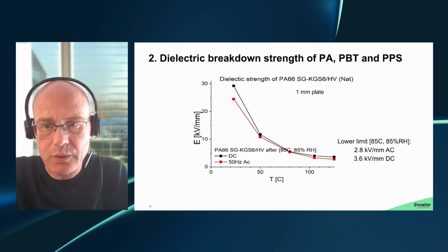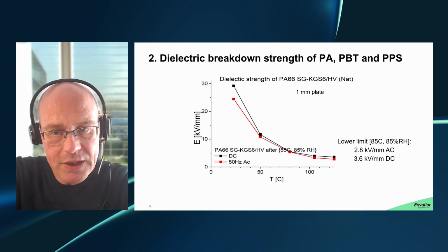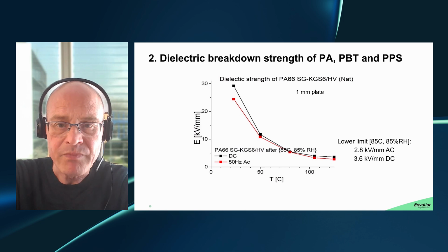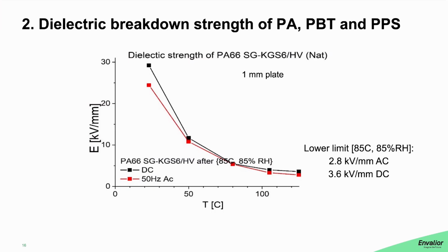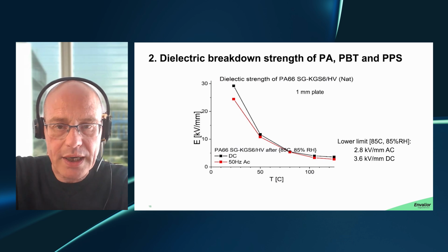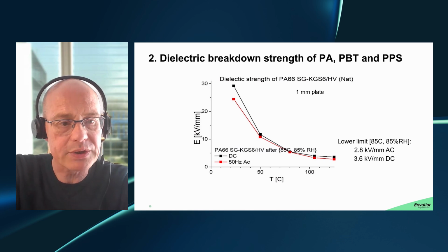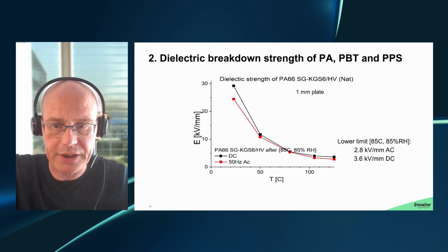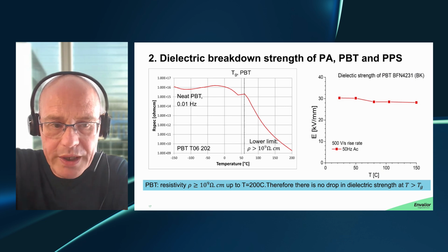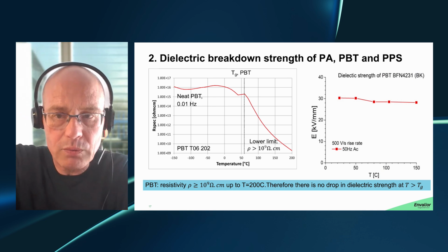Now, just to be certain, we also looked at that in DC. So the previous picture was for 50 Hertz AC. That is reproduced here in the red line. We also looked at DC, that is the black line, and then you see that you more or less have the same strength values. So again, in this particular case, the lowest value is 3.6 kilovolts per millimeter. So in other words, as long as you stay above 2.8 kilovolts per millimeter, you can use this material in your applications. Now, before we move to the conclusions, there are 2 more slides to show.